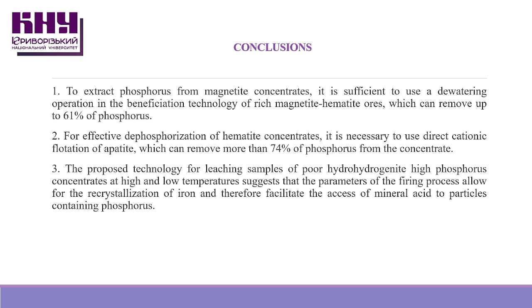First, it is sufficient to use the desliming operation in the enrichment technology of rich magnetite-hematite ores to extract phosphorus from magnetite concentrates, which can remove up to 61% of phosphorus. Second, for effective dephosphorization of hematite concentrates, direct cationic flotation of apatite is necessary. This process removes more than 74% of phosphorus from the concentrate.